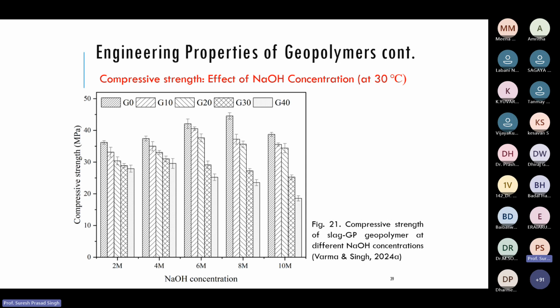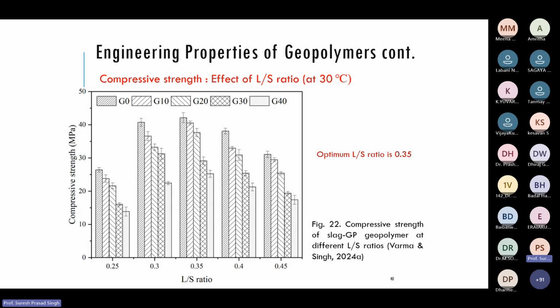So because the release of bonding will be strong, release of silicon will be less, and a particular slag will have a lot of calcium component. So in addition, in the geopolymeric product, if you use slag, we will have hydration products because there is calcium, so we'll get calcium silicate hydrate, calcium aluminate hydrate in addition to the geopolymeric product. But if you replace the slag with glass powder, we will be sacrificing these hydration products, like calcium silicate hydrate, calcium aluminate hydrate, as we got in the cement. But with high temperature, the strength increases. So this gives you the normal temperature at ambient 30 degree. Everywhere they still get less strength if you increase the glass content.